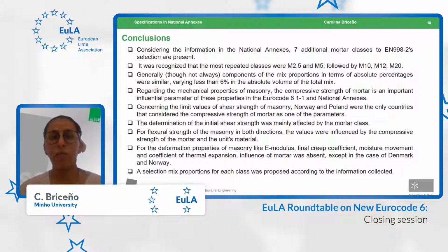Regarding the mechanical properties of masonry, the compressive strength of the mortar is an important influential parameter for these properties, according to the Eurocode 6 part 1.1 in both versions, as well as in the national annexes. Concerning the limit values of the shear strength of masonry, Norway and Poland were the only countries that considered the compressive strength of mortar as one of the parameters. For the initial shear strength of the masonry, we see that it was mainly affected by the mortar class, while for the flexural strength of masonry in both directions, the values were influenced by the compressive strength of the mortar and of the unit material.